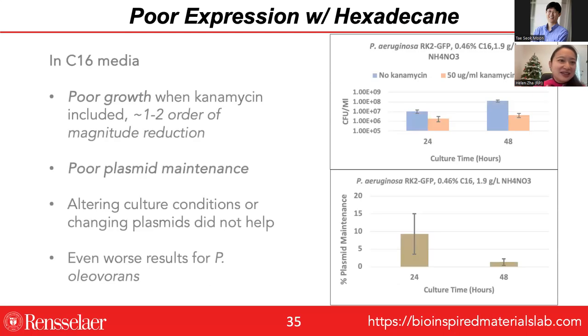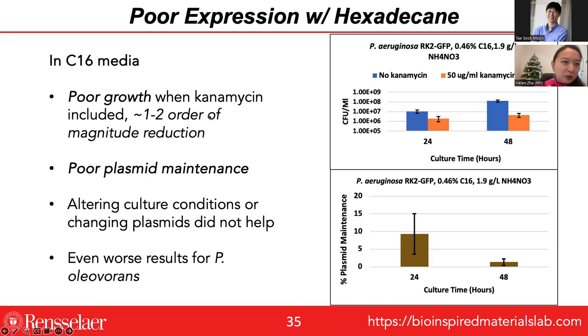We also found that there was rather poor growth when we used an antibiotic in the media for selection purposes. And there was extremely poor plasmid maintenance. We found that altering culture conditions or changing plasmids didn't help with this problem. And we found this problem is even worse for the other strain of Pseudomonas that we looked at. And so all of that pointed to us that we could not use plasmids as a way of engineering this organism to produce our silk. We needed to go with genomic integration.